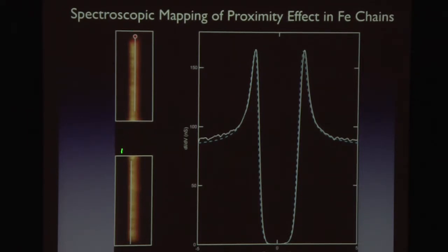So this is a chain, and they often do have defects in the middle of them. You can do experiments where you put your tip at different locations. Here's the measurement, taken just outside the chain on the superconducting lead. This is the energy gap of lead. There are no in-gap quasi-particle states. This is kind of our vacuum, inside of which we are building this object.